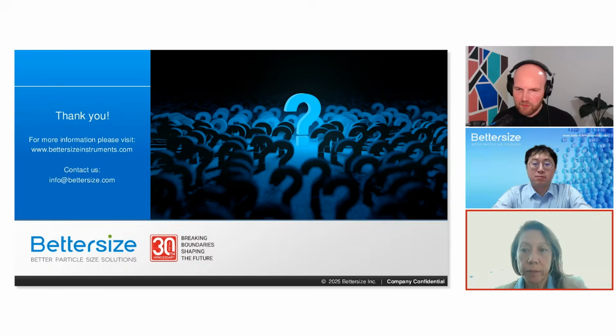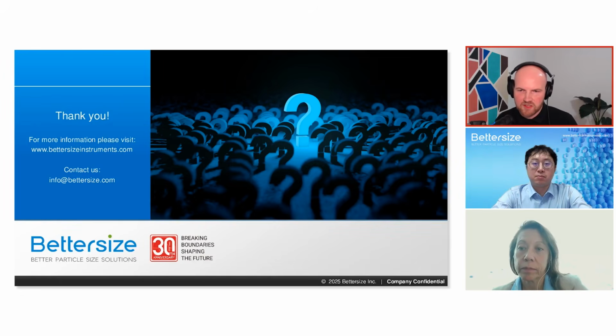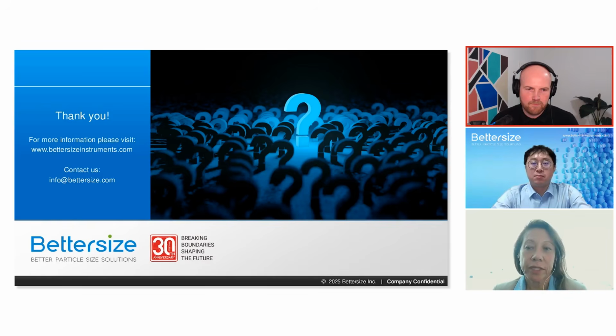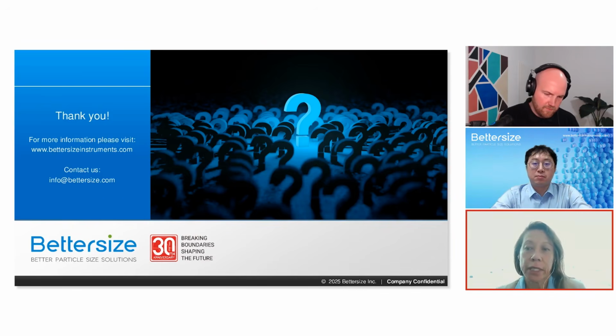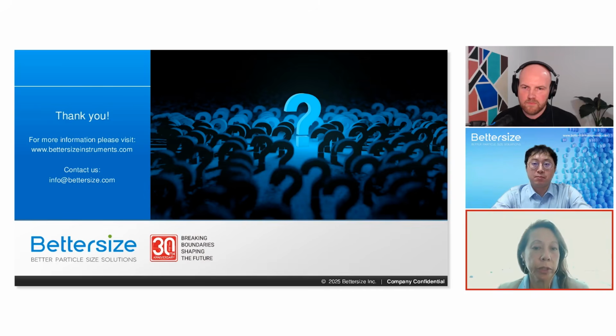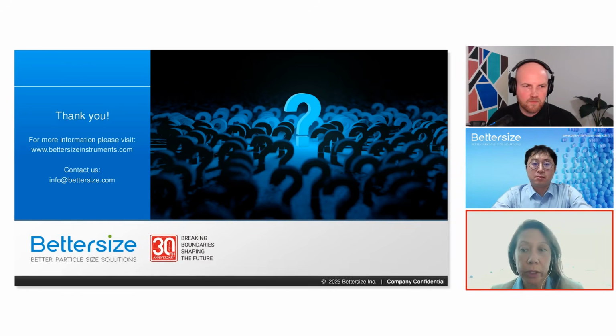Fantastic. And there's a quick follow-up to that one as well. It's asking about the time required. So what is the time required for analysis? Well, as I suggested, generally for particle size analysis, the test only takes minutes. This would include multiple repeats in order to ascertain the consistency, reliability and repeatability of the data. For things like zeta potential and size, for sedimentation studies, typically studies start at an hour, maybe even as short as 20 minutes, but you have the capability to run for hours, days, and even weeks for those kinds of studies. And that is obviously related to the data you want to acquire.